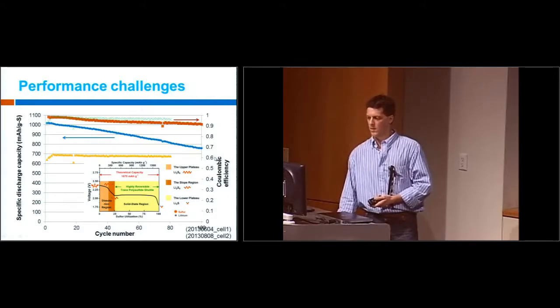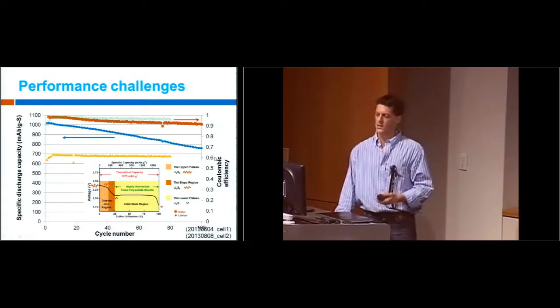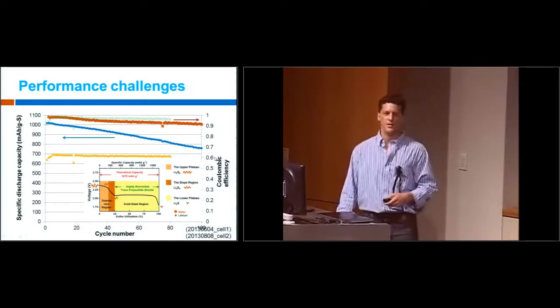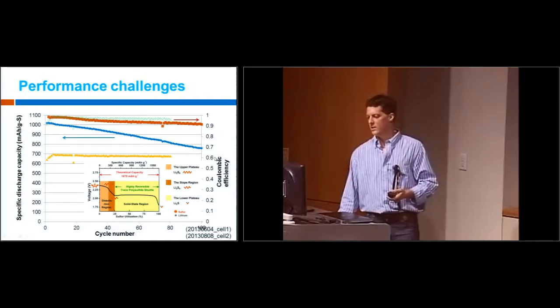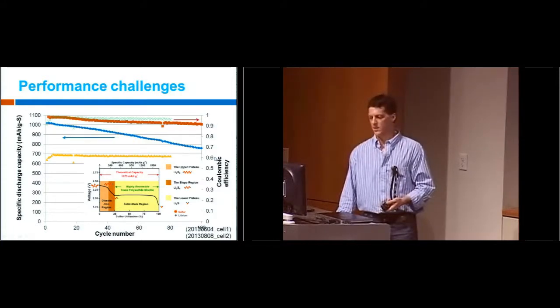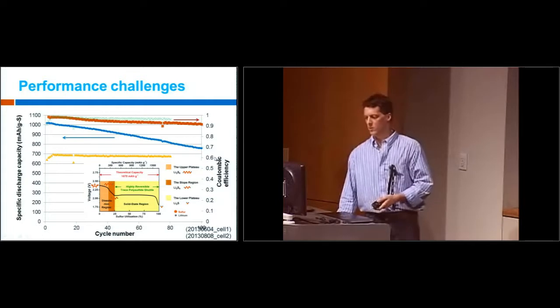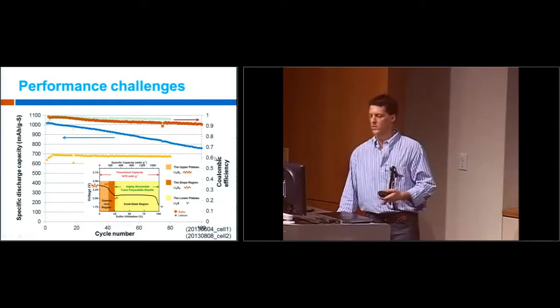There you can see there's some loss, but not very much compared to the loss that you observe with the dissolved polysulfide when you cycle all the way through. So this is a compromise, and this is very typical of what you face as a battery researcher: it's very difficult to find something where you get everything that you want. Here we've sacrificed a bit of capacity, but the performance is very constant. This is only 80 cycles now, but we have other data that shows you would expect this to remain pretty constant over several hundred cycles.